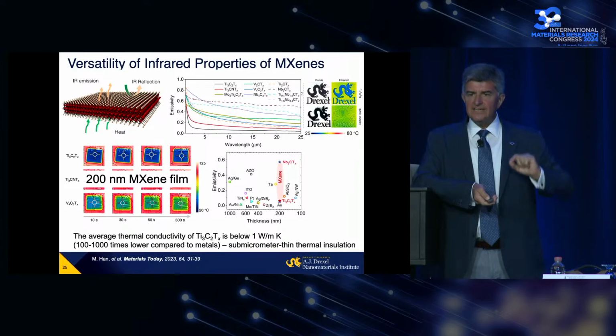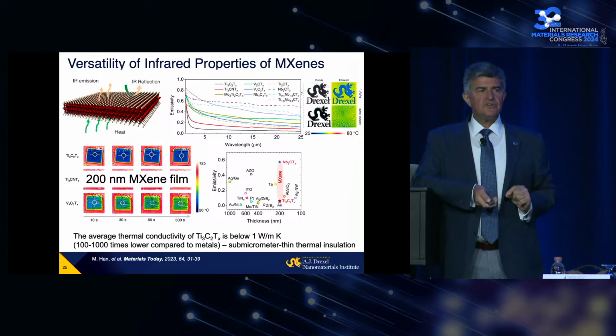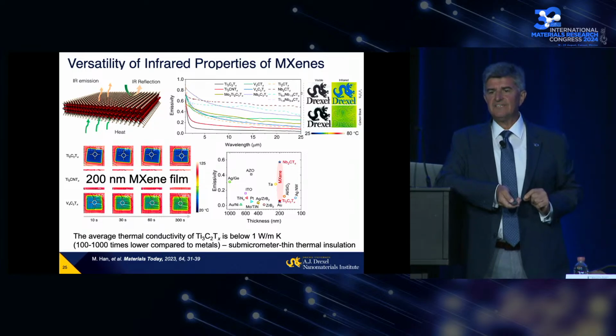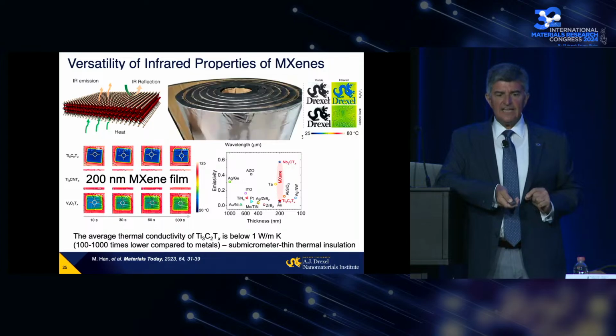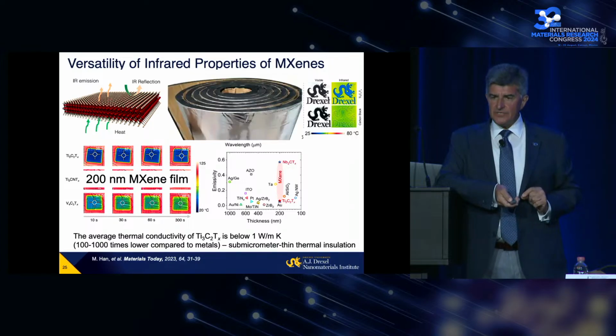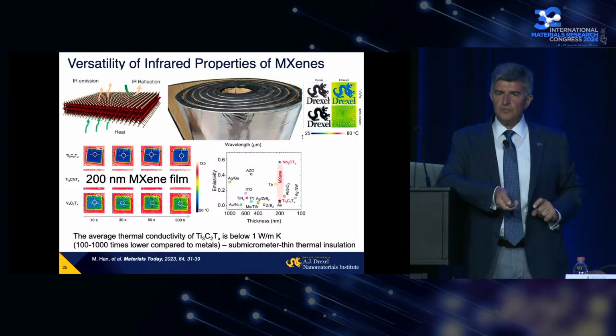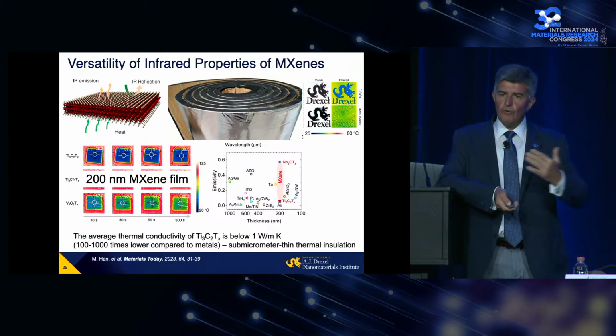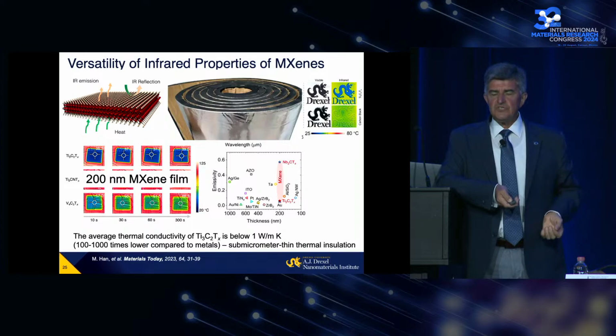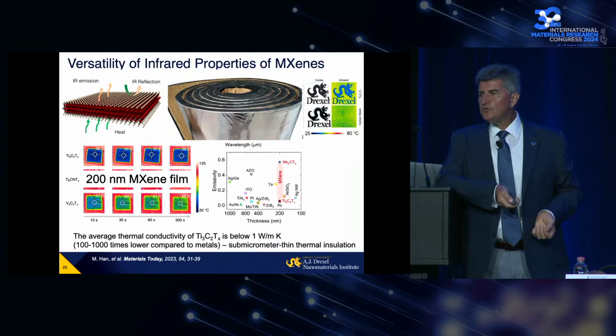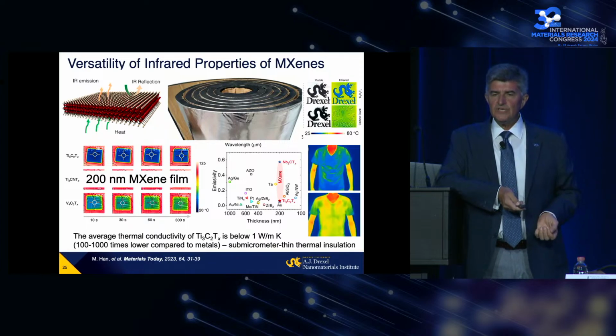Because being metallic, these materials have thermal conductivity below 1 watt per meter Kelvin averaged in the field. As a result, they can outperform potentially any material. Instead of thick thermal insulation and then low emitting aluminum on the surface, we can make a film which is 100 times thinner than a human hair.